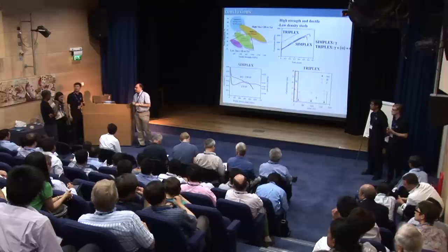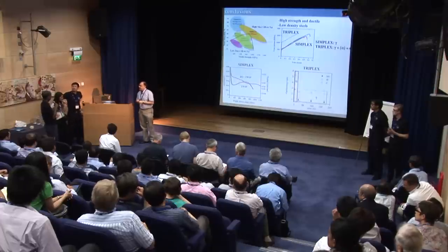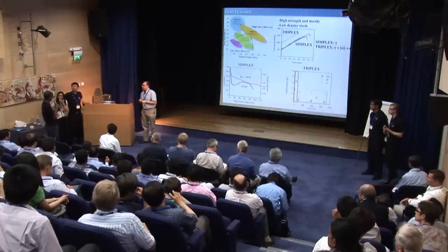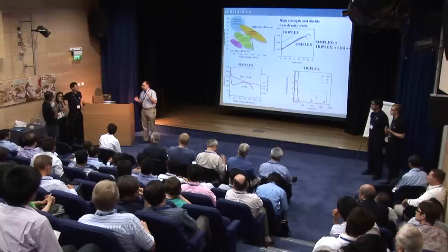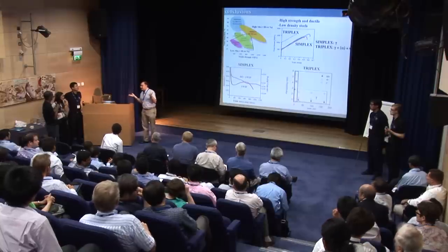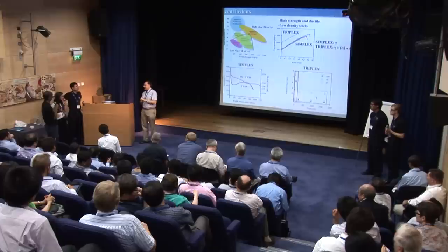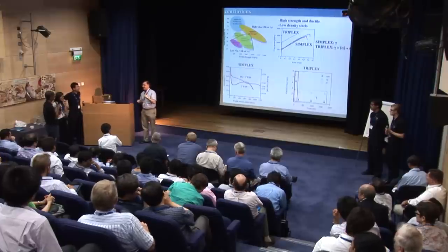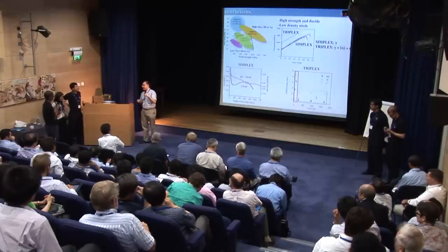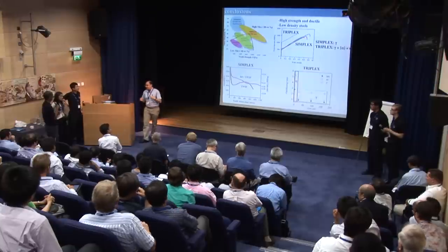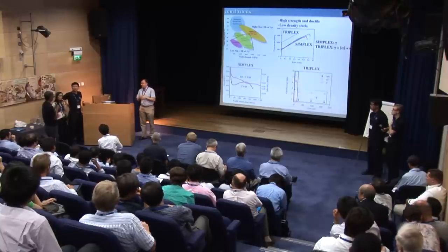I don't mean for high temperature applications, but the passage of dislocations. Kappa is not a particularly penetrable particle, right? Yeah, it depends on the size of these particles. But in terms of ordering, it's extremely ordered. So I guess that the anti-phase boundary energy will be very, very high. So that's why it will not be very penetrable. But my comment is in terms of controlling the lattice mismatch through the chemistry, this is something that is ongoing.